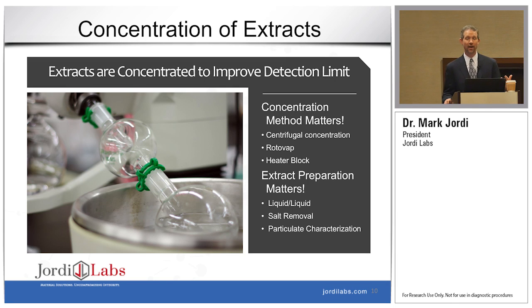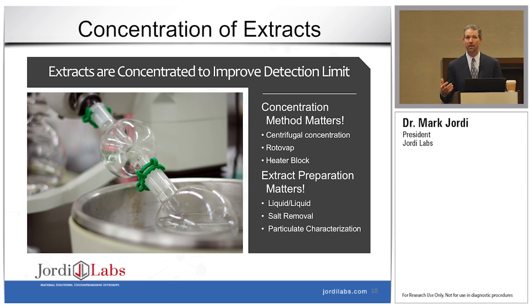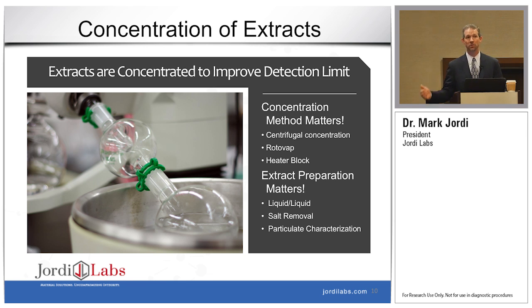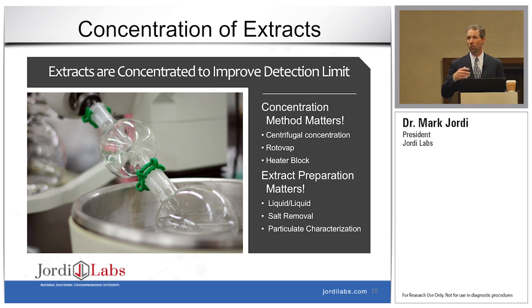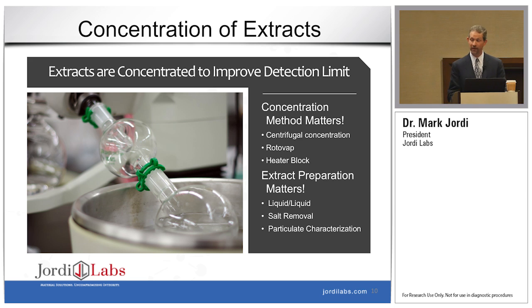Once we conduct those extractions, we have to take those extracts and prepare them to go into our instruments. Sample prep is really the unsung hero in an analysis of this type. People often don't think about this very carefully. One of my passions has been to consider how the choices we're making are affecting the results we're observing. In particular, when people take that extract and begin to concentrate it, or do a liquid-liquid extraction or a solid-phase extraction — what did we lose? What did we not capture? And therefore, we did not include that in our toxicological evaluation. There are a lot of important decisions that have to be made before you ever inject these onto your instruments, and that can have a very large effect on what you do and don't detect.